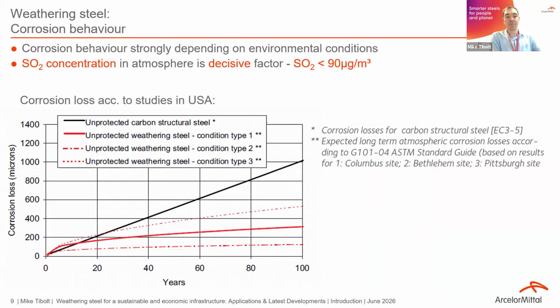Coming now to the corrosion behavior. The corrosion behavior strongly depends, of course, on the environmental conditions. A decisive factor is the sulfur dioxide concentration in the atmosphere. Of course, too high a content would jeopardize the formation of this oxide layer, and therefore the threshold value to ensure the good formation of the patina is below 90 micrograms per meter cube. Considering now, at least in the European countries, that the industry has strong filters installed, the sulfur dioxide content is lower than this 90 microgram per meter cube. So this should not be a problem for the formation of the patina.